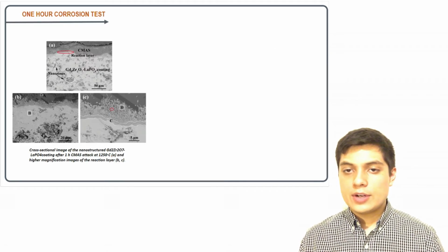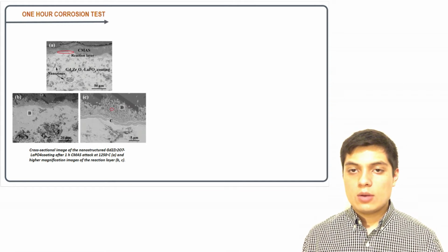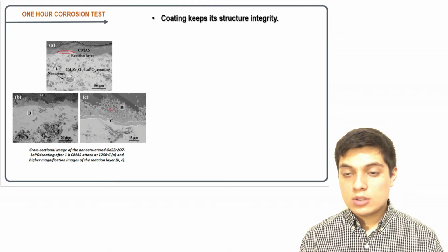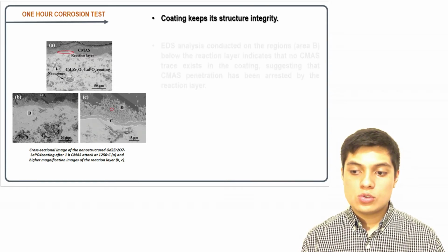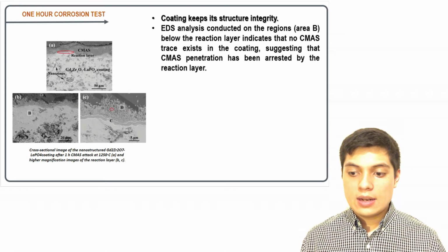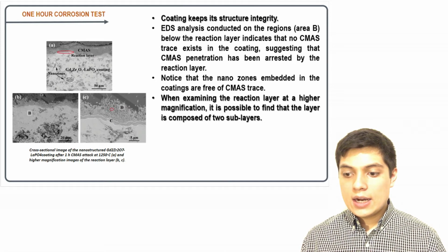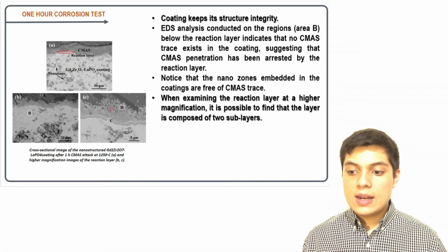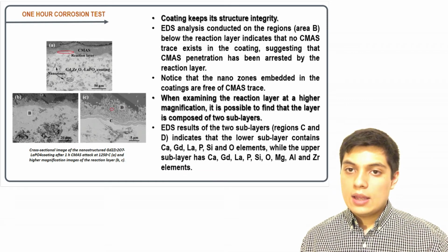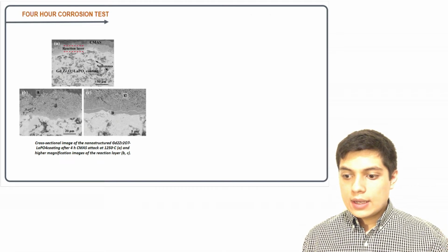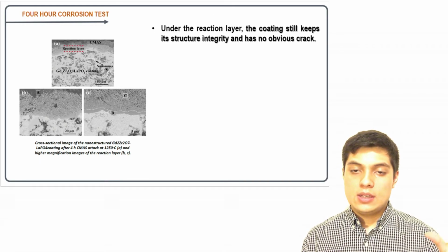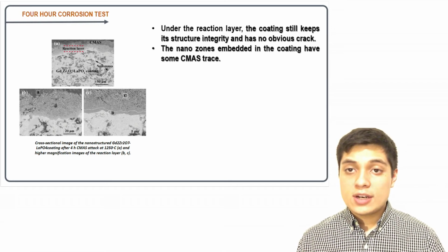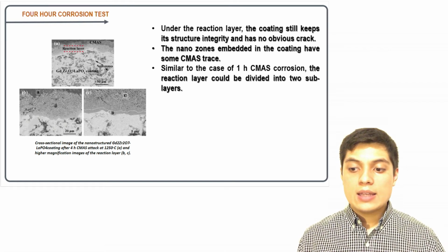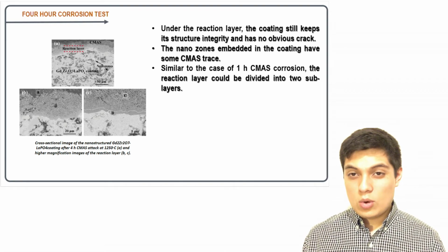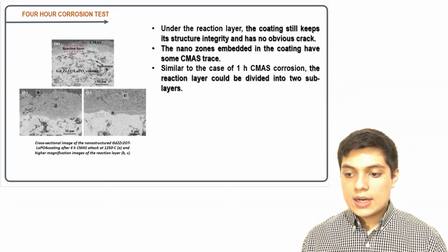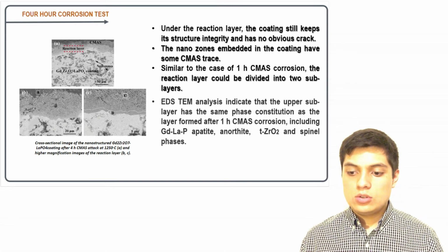So the first analysis conducted was on the sample of the 1 hour corrosion test, and the main point of this test was that the coating keeps its structural integrity. And one important fact is that when they examined the reaction layer at a higher magnification, it was possible to observe that the layer was composed of two sublayers, the upper layer and the lower layer. In the 4-hour sample test, the coating still keeps its structural integrity and has no obvious crack. Another important point was that the nanozones embedded in the coating have some CMAS trace, and similar to the 1-hour test, the reaction layer of the 4 hour test could be divided into 2 sublayers.